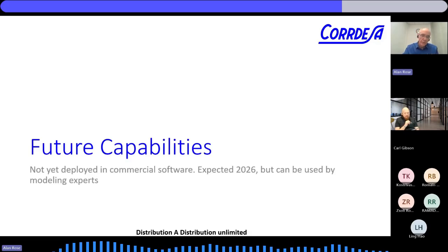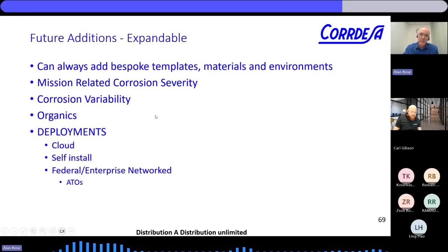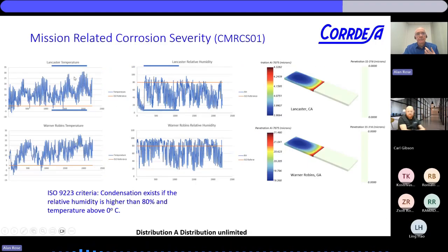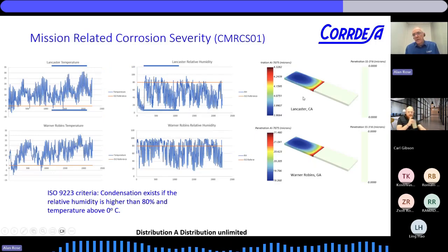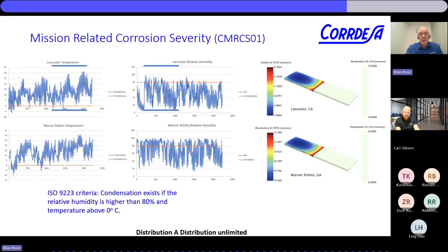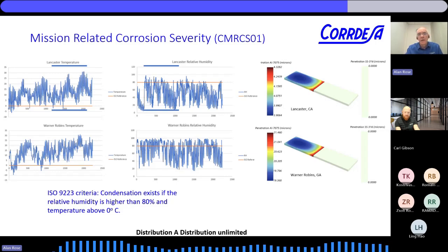Back to the software, I could just point to a couple of future capabilities that might be interesting. You put data in, you get results out. It's very deterministic, isn't it? So what we've done, rather than assume a 24/7, 365 time of wetness, let's look at the weather data. So now we have a tool that reads in the weather data and applying an ISO 9223 where condensation is expected above 80%. We can march through that, and we can look at the impact of what that corrosion rate would be depending on where that asset is stationed.